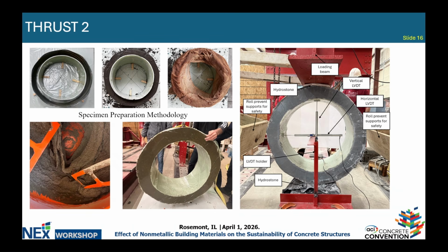If you see the top 3 pictures there, that's the cementitious grout. Filled in, the grout annuli was completely occupied and cured with a wet burlap. That is pretty much, well, not in the industry, sometimes maybe a curing agent, but 28 days of curing is highly unlikely, but we've tried our best to represent more of a laboratory and high quality control. The last 2 pictures that you see here on the bottom are the polymeric concrete that was mixed and the annuli completely filled with that, room temperature cured.